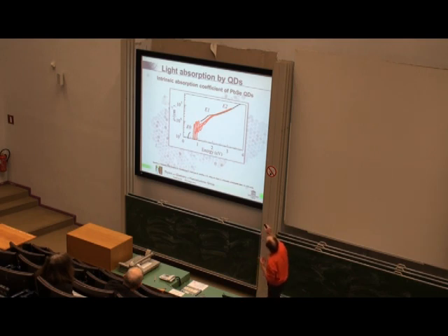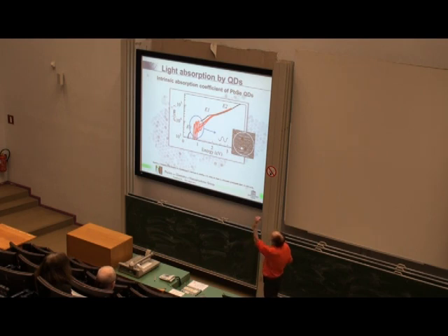You see two things. The first thing is, the different curves are for differently sized particles. This is what we have been talking about. This is the nanocrystal with its discrete energy levels, and you have a photon coming in, and you can absorb light, you can transfer the electron to a higher energy state. The peak that you have here corresponds to that transition for smaller and smaller particles. So the smaller the particle, the more this peak is shifted to the blue. And so absorption across the band gap is size dependent. That's also the color change you saw in synthesis. It's this absorption onset there. The particles grow bigger, so it shifts to the red.